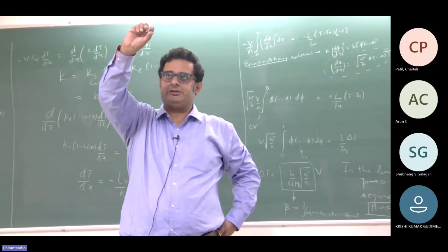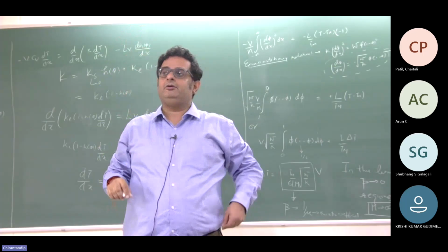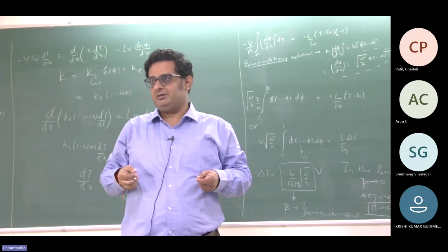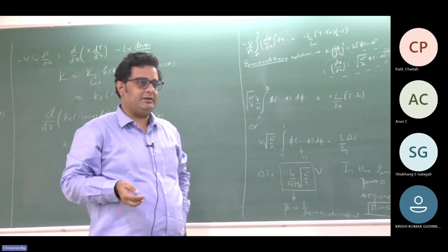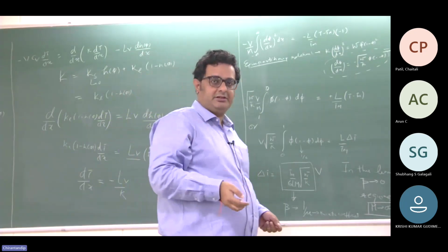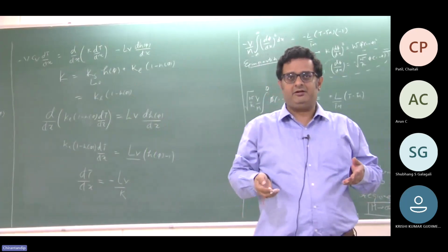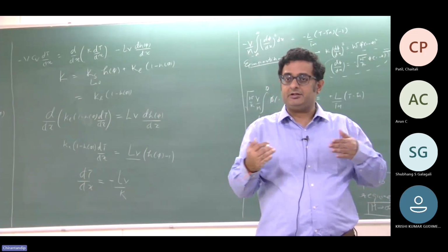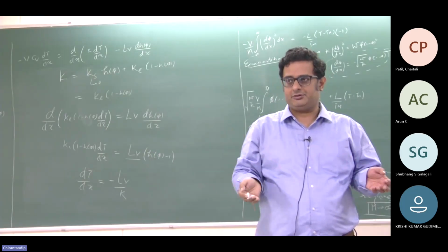And if there is therefore the jump at the interface, where I think the interface exists, which is phi equal to 0.5, you are having a discontinuity of temperature at the interface. Typically, chemical potential and temperature are continuous at the interface. That is a typical condition that you put when you integrate a phase field interface.